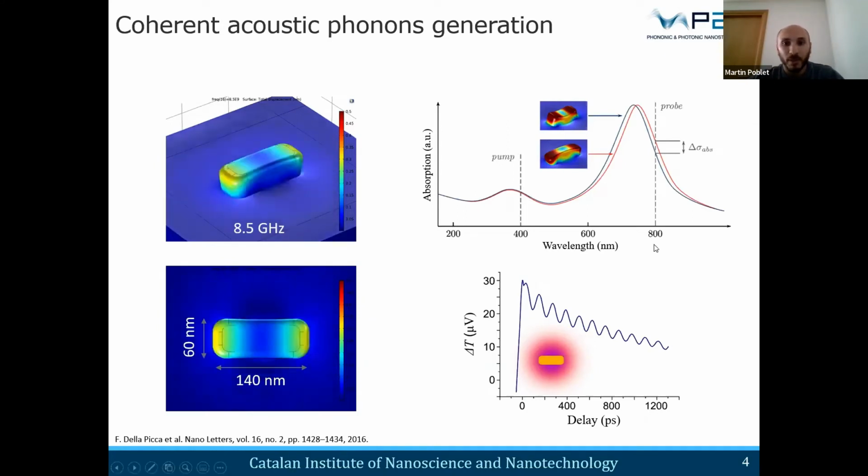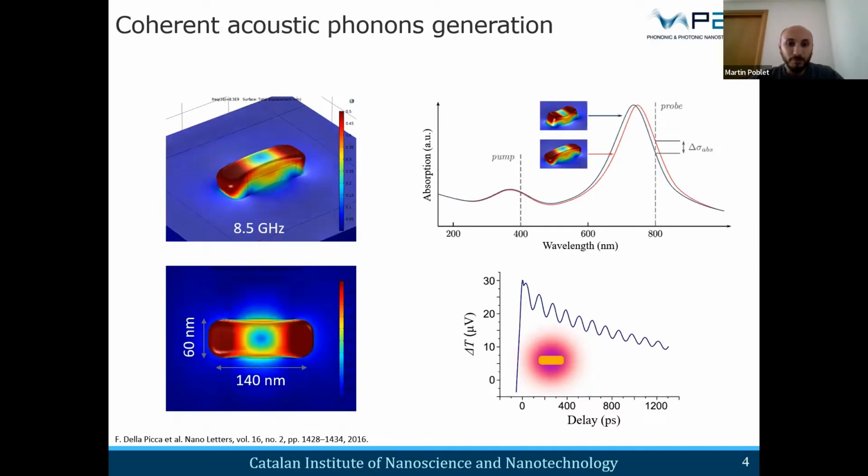So the coherent phonon dynamics can be studied by pump-probe measurements, where the pump will be the excitation pulse and the probe will measure the state of the antenna at a given moment, as we can see in this typical probe signal where the differential transmission was acquired.